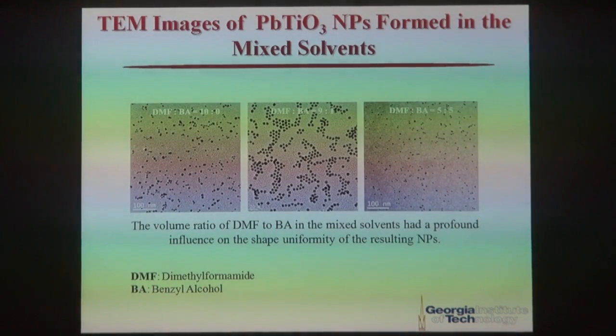So now, quite intriguingly, what we found is the mixed solvent we used to do the reaction to make nanoparticle actually had profound influence on the quality of the nanoparticles we produced. So when we use DMF, dimethylformamide, as the only solvent to do the reaction, we saw the nanoparticles with irregular size and shape produced. However, when we add 10% benzyl alcohol, BA, in the system at DMF to benzyl alcohol 9:1 ratio, we saw the particles with the best uniformity was produced. However, if you continue to add benzyl alcohol at DMF to benzyl alcohol 5:5 ratio, you see the nanoparticle again now has reduced the regularity.